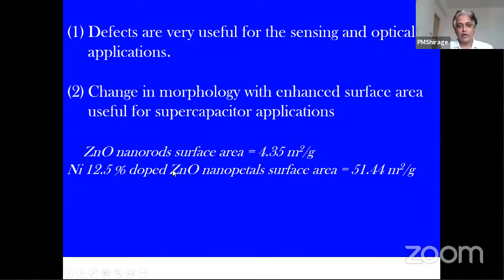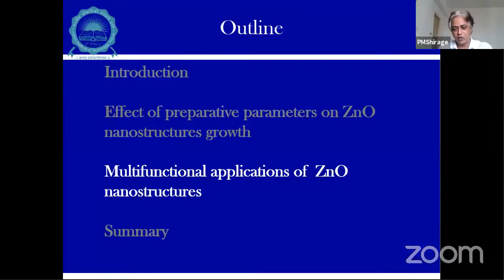So zinc oxide nanorods have a surface area of 4.35 meters squared per gram, and if we replace this zinc oxide with nickel 12.5%, then the surface area changes from 4.35 to 51.44 meters squared per gram. So it means that because of doping, the surface area is changing. Rod-like morphology is changing to flake-like structures. That is very useful for applications like energy storage.